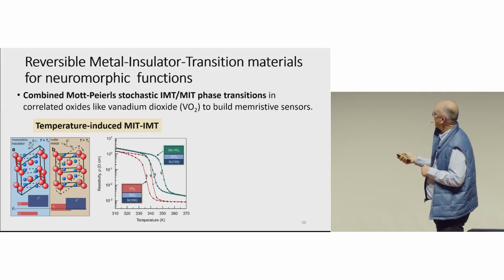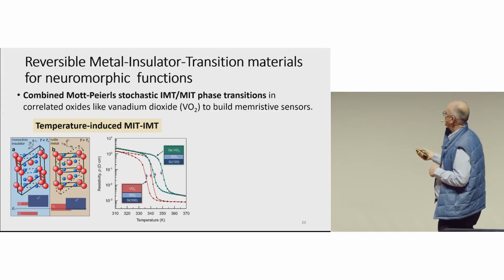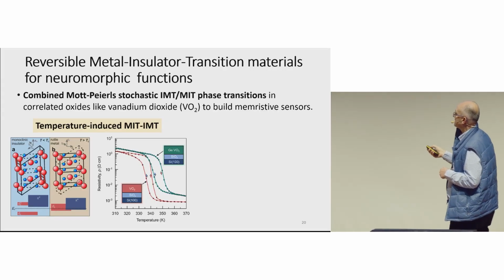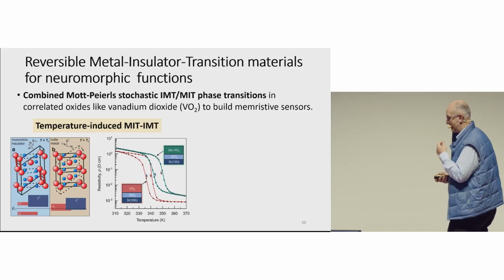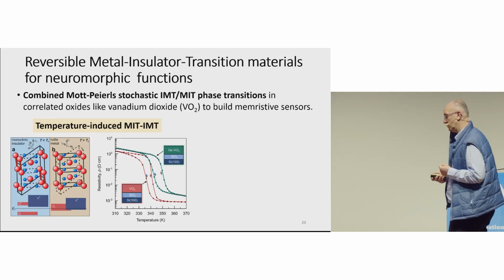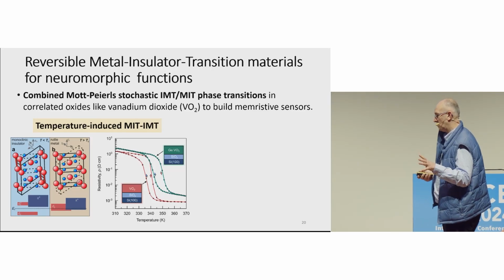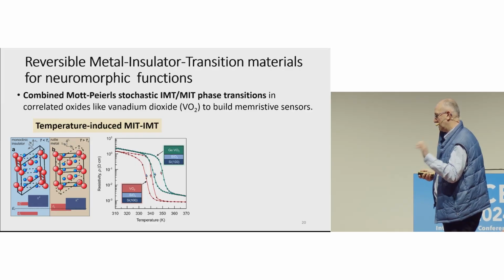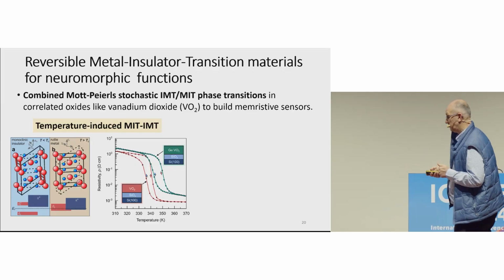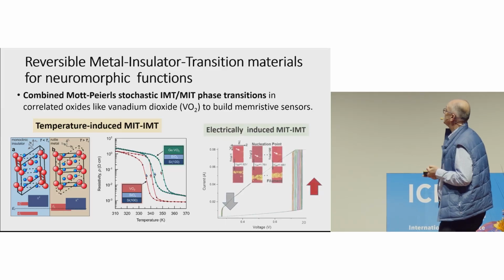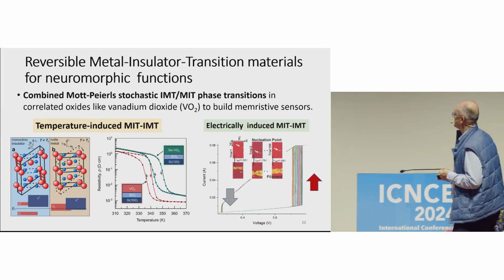what you have here on the right, left-hand side: the band gap collapse that happens at a certain temperature, with a contrast in resistivity of 3 orders of magnitude. And temperature is one stimulus, but there can be other types of triggering of this effect. And one of the most interesting is that you can electrically induce this.